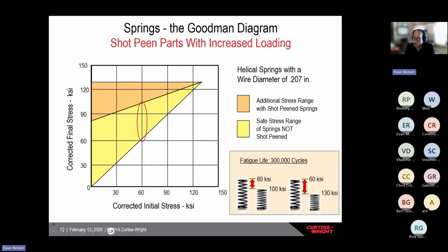So this example here just shows, let's say that this compression spring, throughout its loading, goes under full deflection, the peak stress is 100 KSI. So let's say that this situation here gets 300,000 cycles. So now with shot peening, what you can theoretically do is increase the loading on the spring. So let's say now you're compressing it further, such that your peak stress is 130 KSI. So you're putting 30% more loading on that spring. Theoretically, you might be able to achieve the 300,000 cycles you were getting under the lower stress loading.